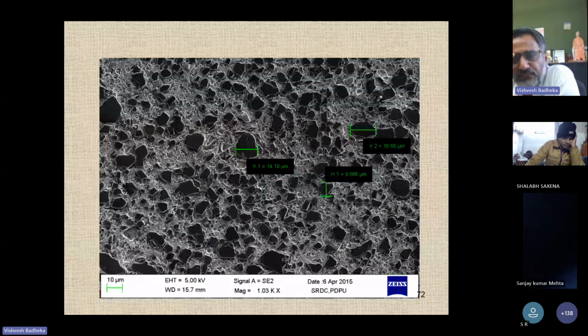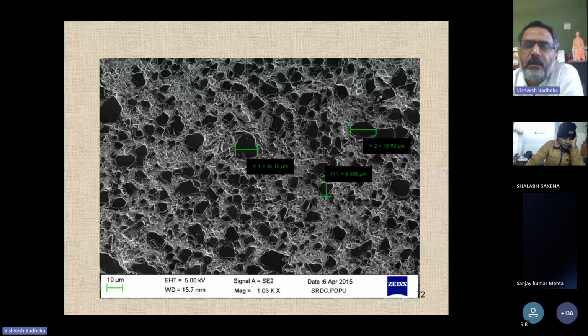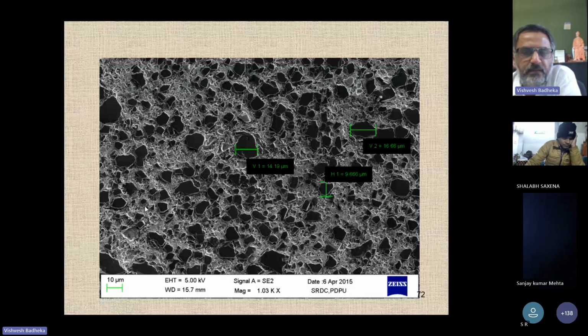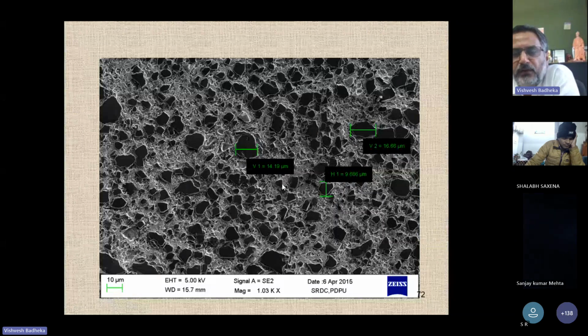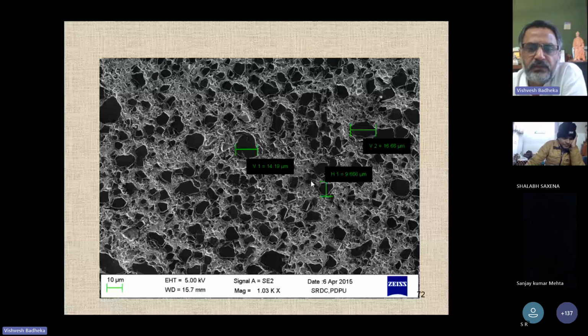So this is how you can see one more picture, a scanning electron microscopy picture, which shows that when you go for friction stir processing, these reinforcement particles, in this case boron carbide particles, themselves also get fragmented, right? You see, some particles are very fine, some particles are bigger. Say, for example, if you started with a 20 micron particle, those particles also get fragmented because you are processing 1 time, 2 times, 3 times. So those powder particles also get fragmented.